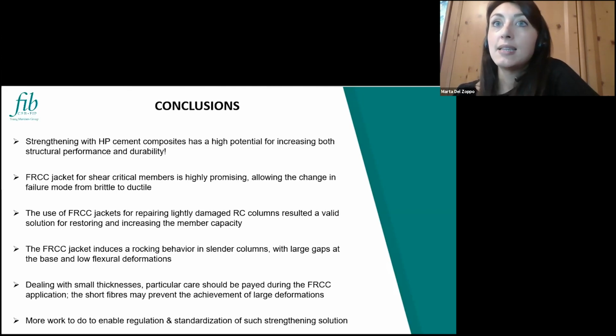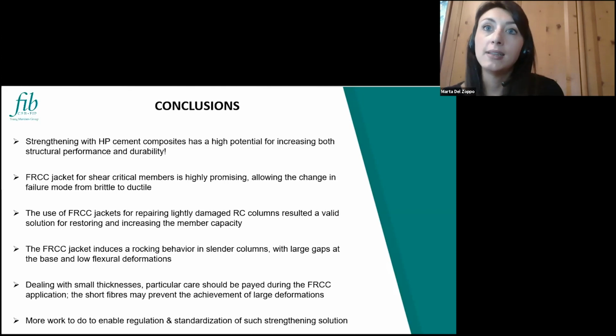These kinds of systems can also be used to restore and recover the capacity of seismically damaged members, also increasing the capacity if a proper anchorage system is adopted. But the point is that this kind of jacket is changing the behavior of the members. So we are no longer dealing with flexural members that develop flexural deformation, but we still have deformation at the base of the member in terms of base rotation and a sort of rigid rocking behavior of the entire member itself.